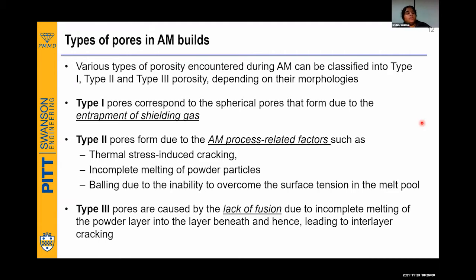So what happens is, as we saw, the first layer of powder is applied, and we are rastering the laser over it. And the second layer we are applying, and again while rastering the laser in the second layer, there is incomplete melting. That is, there is no good fusion between the consecutive layers. So this is typically an interlayer cracking. And these interlayer cracks will be generally of lesser circularity. So it won't be as spherical like the type 1 pores, but they are of lesser circularity.